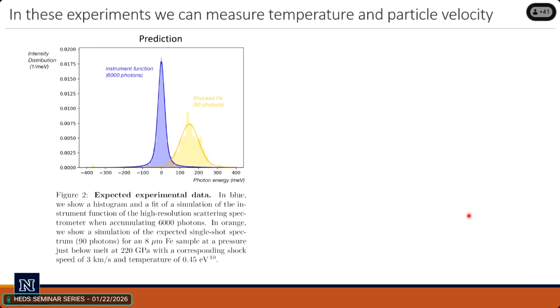But the long pulse laser at MEC can only fire once every 7 minutes. So, you know, there's pros and cons of that. But what you get when you do that is not just the temperature from the broadening, but you also measure the particle velocity of your shock, because you see a shift of the spectrum, because it's all moving with one velocity, and then you see the broadening.